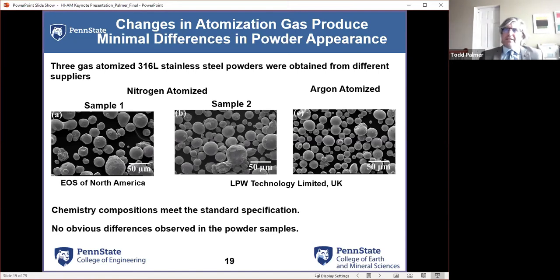Now, just looking at these powders, the chemical compositions, the chemistry, I have two different lots. I chose two different manufacturers that gave me two different nitrogen atomized 316Ls. And I actually found one producer who I think was playing around, and I got lucky. They just happened to have some argon atomized 316L, so they used argon as the atomization gas. And so I said, hey, send me that. We want to take a look at what happens.